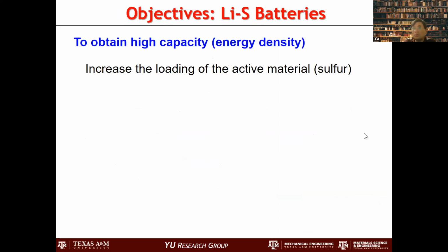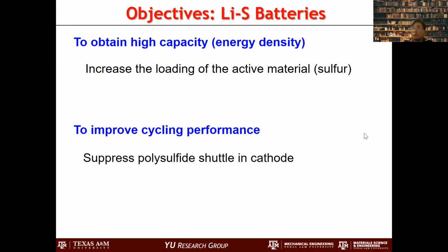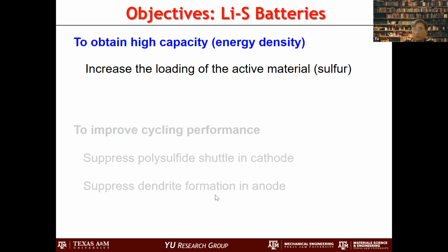What people actually use here is NMC and or LFP, and in particular NMC requires cobalt, and those things are expensive. So our objective is to obtain higher capacity and energy density, and then we can load more sulfur, which is the active material. Another problem is that we have to cycle much longer, so we have to improve the cycle life. One of the problems for lithium-sulfur battery is polysulfide shuttle in the cathode, and we want to suppress this. Also, there is the fire risk, and typically in lithium-ion batteries, one of the main causes is dendrite, and we want the dendrite to be suppressed. That's another thing that we want to suppress and minimize.